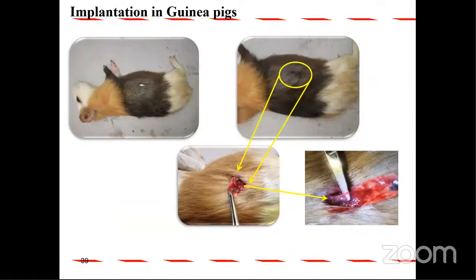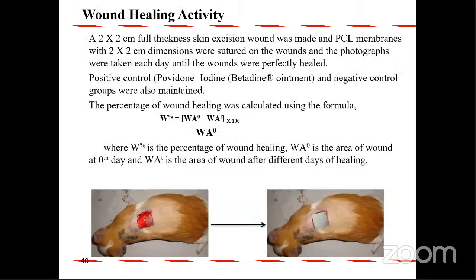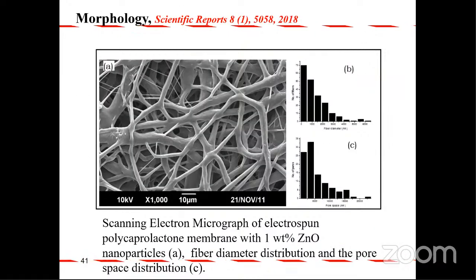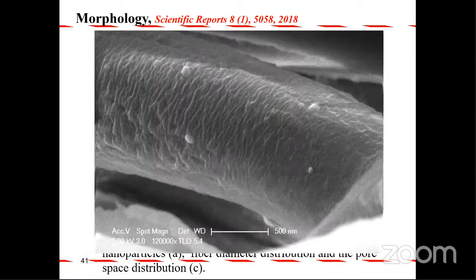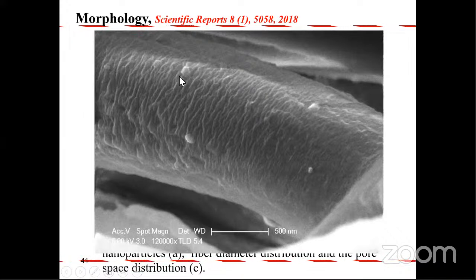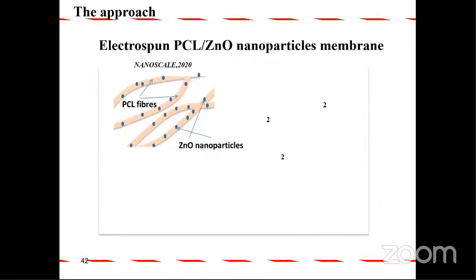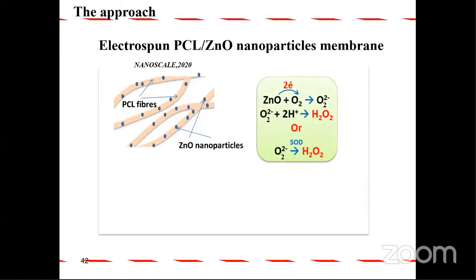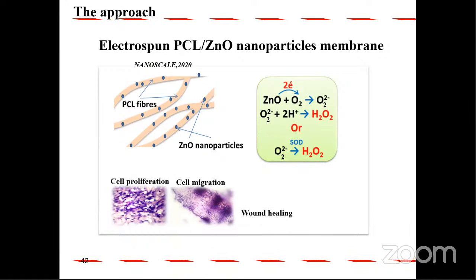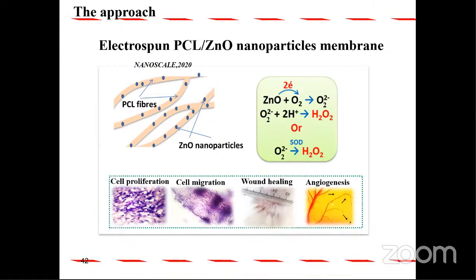We also did a lot of in vivo studies with guinea pigs. You can see we have made the wound and the wound has been closed. This is the internal structure of our tape, highly porous. We also added nanoparticles to accelerate the healing process. For example, zinc oxide we added, just 1%, 50 nanometer size. Excellent effect on wound healing, because zinc oxide can react with oxygen forming hydrogen peroxide. That is actually giving lots of interesting results: cell proliferation, excellent cell migration, excellent wound healing, and angiogenesis.